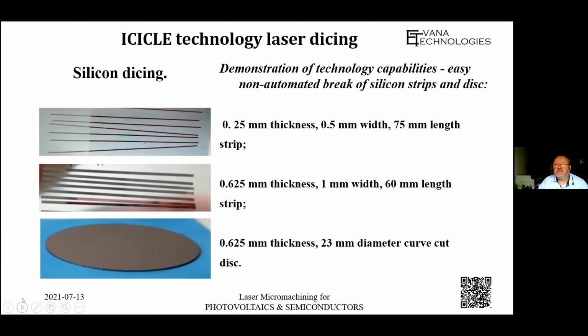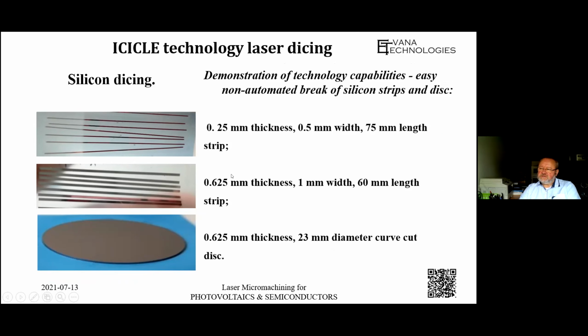Next is silicon, also a very big group of devices, which really underlies all electronics and microelectronics. You can also see our achievements for dicing quality: 0.25 millimeters thickness, 0.5 millimeters width, and a 75 millimeters length strip. After dicing, you can easily break this without any cracking or destroying of the line. We can also do this round shape dicing.